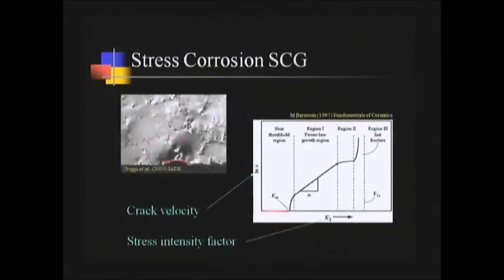And what I'm showing you here is a fracture surface from a piece of porcelain that we broke in my laboratory. And you can see on the surface the pore, the flaw that generated an initial crack and began growing slowly through the material while it was under stress. And if you look very carefully, you can see, and to help you, I've drawn some red arrows. This is outlining the size that the crack grew to before the material broke.